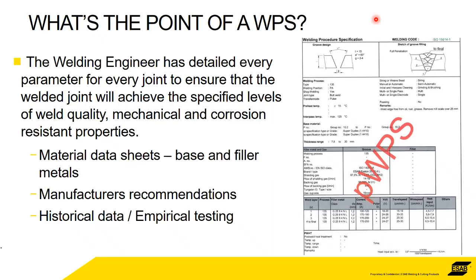It uses the data sheets on the base and the filler material. All the manufacturers of filler metals and any kind of sheet, plate or bar produce data sheets giving their recommendations. They have the properties that the base material is supposed to have, their recommendations for welding, and alongside that, historical data. Usually this has been welded before, the design is not new, for example, so you can use historical data. But ultimately, depending upon the position and the requirements of the weld, empirical testing. You have to prepare welds and test them to destruction to make sure that they're fit for purpose.